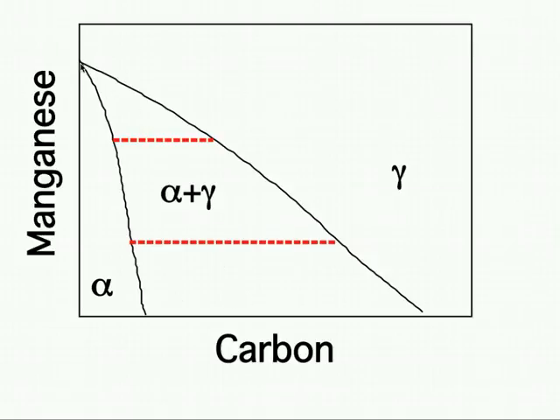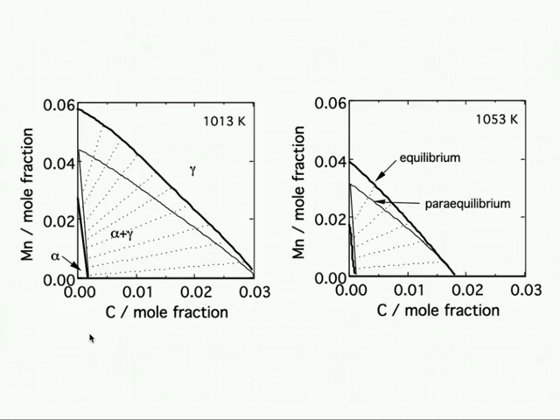Notice also that this phase diagram meets at a point, and that's because in the absence of carbon and the fact that the manganese doesn't move, there's a unique concentration of manganese where the ferrite transforms into austenite. And if we superimpose the equilibrium and para-equilibrium phase diagrams, then you can see that they also meet on the horizontal axis here where the manganese concentration is zero, because there's no difference between equilibrium and para-equilibrium when there is no manganese in the material.